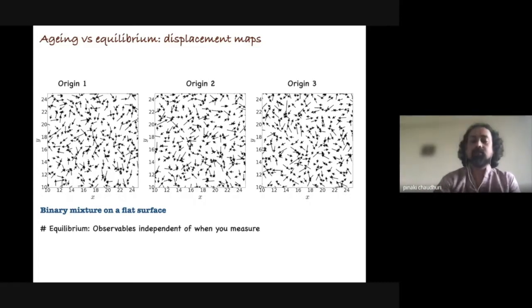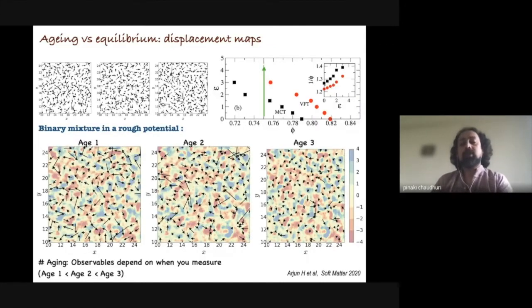Any observable would be independent of when you measure. On the other hand, if you go to a glassy system, and we have studied this in the context of a mixture of disks in a rough potential, if I quench across this rough potential, what happens is that as I go to increasing age, the displacement maps change very much. In other words, the observable depends upon when you make the measurement. If I go to older and older systems, the amount of displacement, given by the size of the arrows, is much less than what was happening at the earlier age.